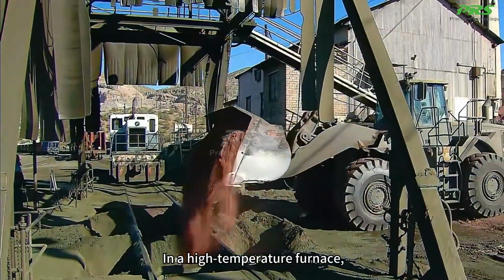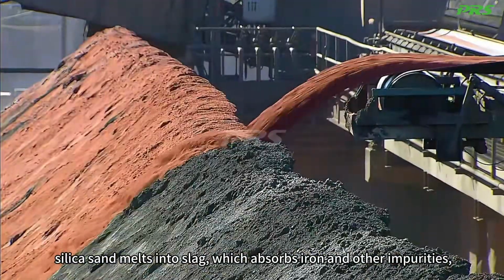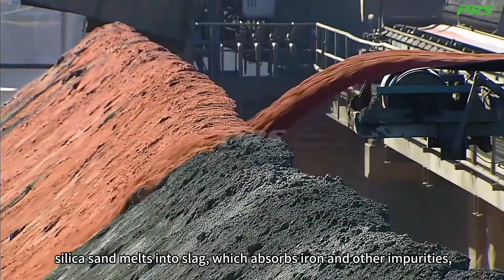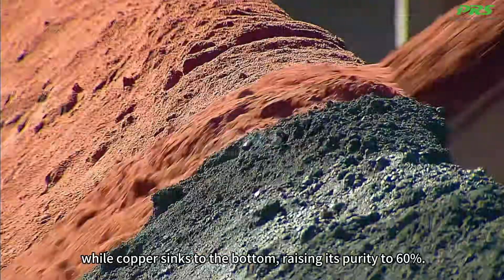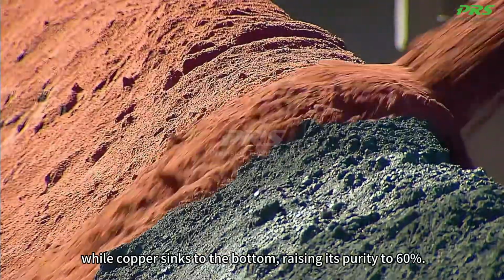In a high-temperature furnace, silica sand melts into slag, which absorbs iron and other impurities, while copper sinks to the bottom, raising its purity to 60%.